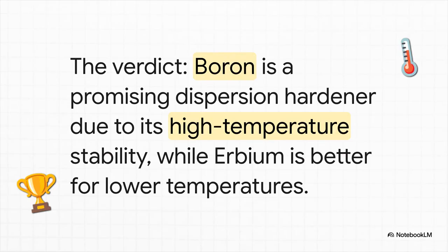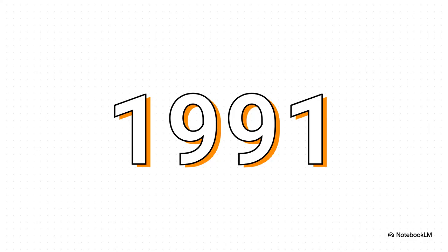So the conclusion was crystal clear. Boron was the more robust, more reliable strengthener, especially if you need something to work in a high-temperature environment like a jet engine. Erbium worked, for sure, but that unpredictable transformation made it much better suited for a narrower, lower-temperature job. And what's just amazing to remember is that all of this incredibly detailed, atomic-level detective work was being done back in 1991.